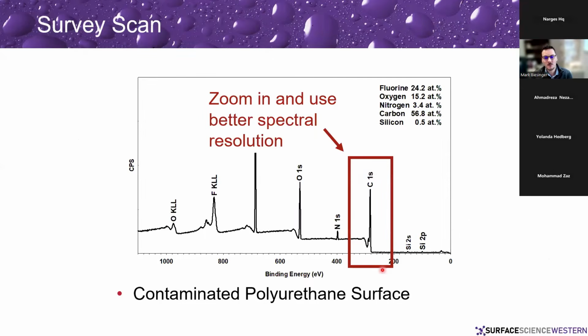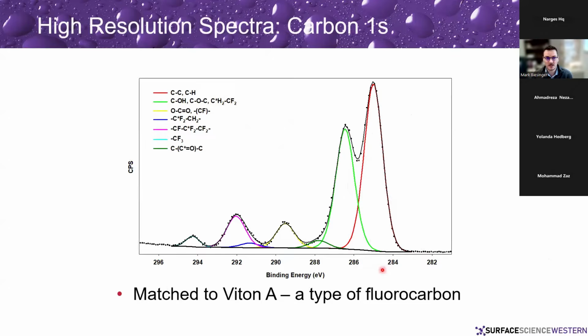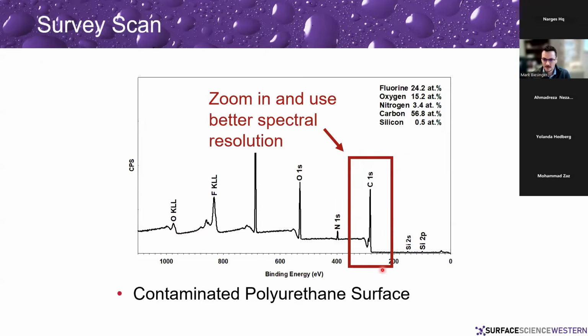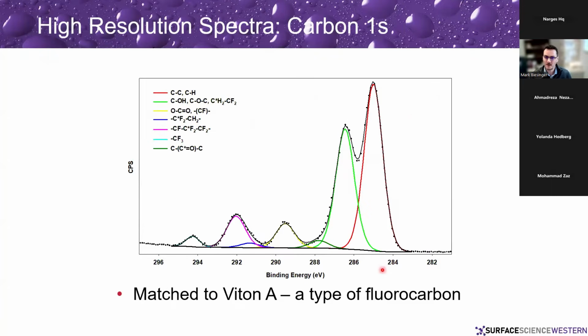So if we go into looking at the survey scan and we zoom in and use a much better spectral resolution, we get what's called a high resolution scan. So this is a high resolution scan of the carbon 1s signal. And you can see that in the survey scan, we see a peak with a little bit of structure, but when we zoom in, we've got this multiple structured peak here that can then be curve fit